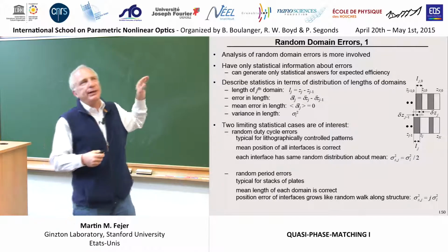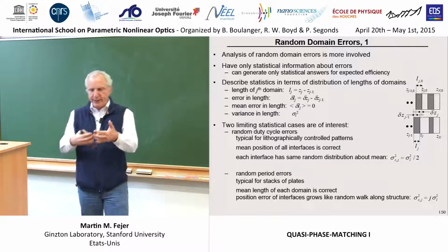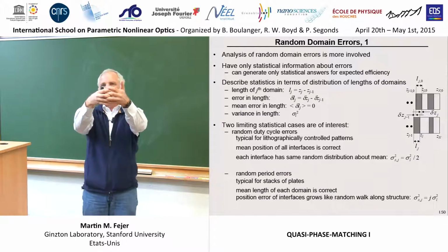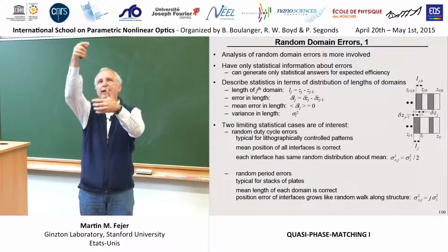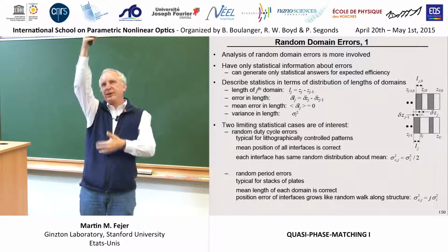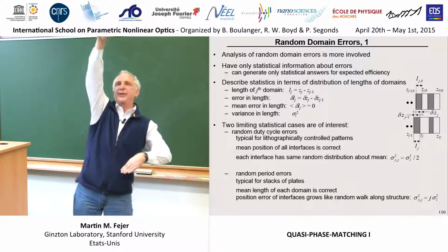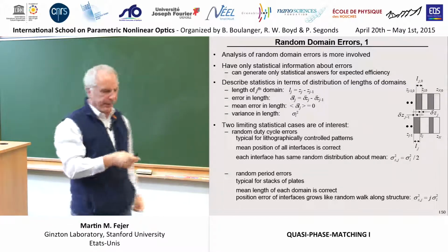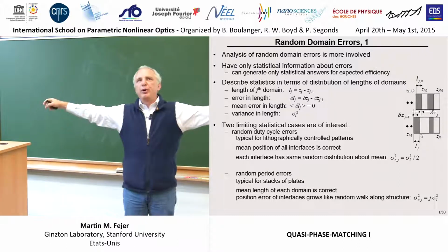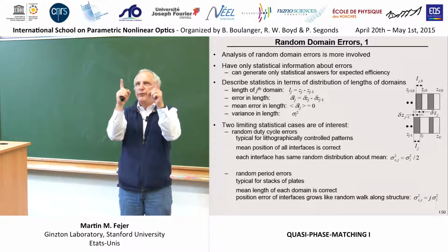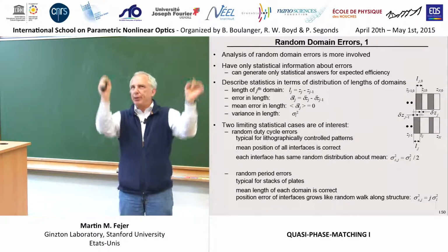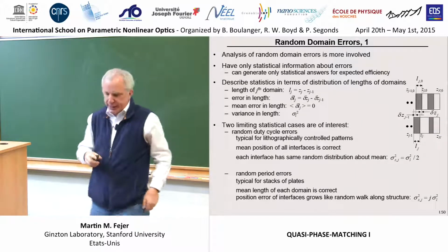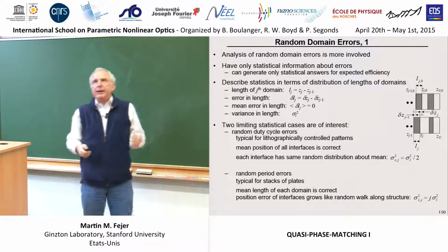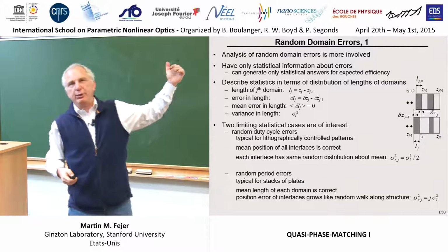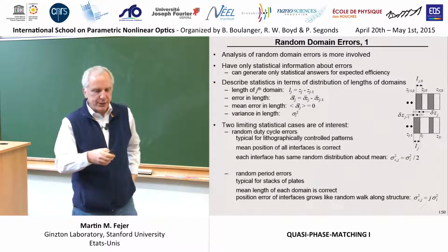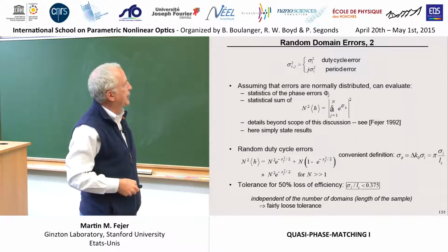So there are 2 kinds of domain errors. The kind that afflicted melt-grown crystals and made them work so badly, it's like stacking up a bunch of coins of slightly different thickness. The more coins you stack up, you're sort of randomly walking this edge away from where it belongs. The more domains of random error you stack up, the farther the jth interface is from where it belongs. You could call that a random period error. The other possibility is the long-range order is perfect because it's set by a lithographic mask, but during the formation of the domains, the edges don't quite line up with the edges of your mask. A little jitter in the domain formation. That you might call a random duty cycle error. Those are more common in the modern era because people don't usually melt grow these things. They're done lithographically patterned. And so let's just focus on that case.